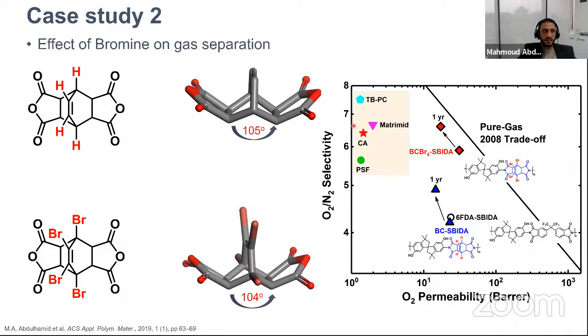These are commercially available materials that have been used in industries for air purification, oxygen-nitrogen separation. We can see our material is performing very close in terms of selectivity, in the 6 to 7 range, and even higher, maybe 10 times, in terms of permeability. So we figured out that any change in the polymer structure could have a very significant effect on the performance.